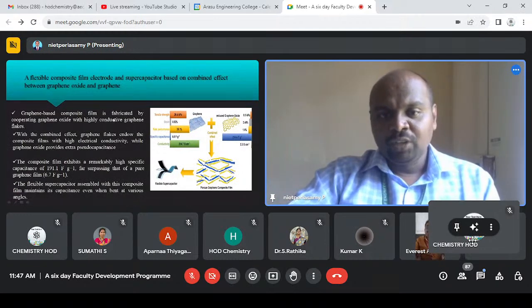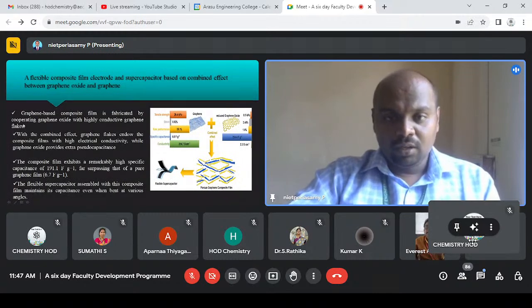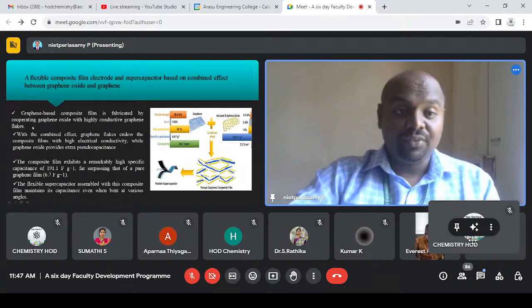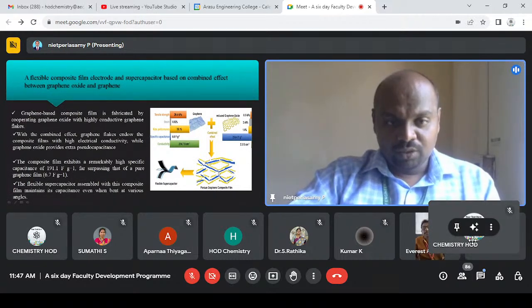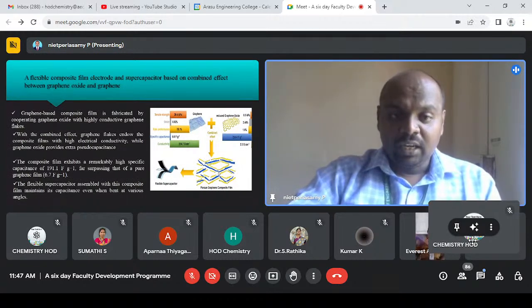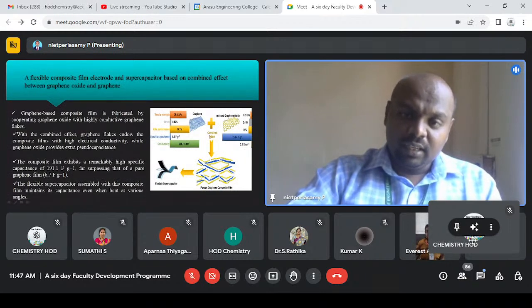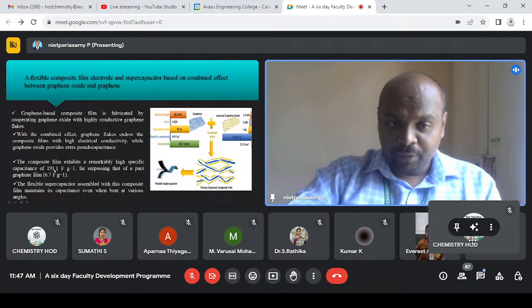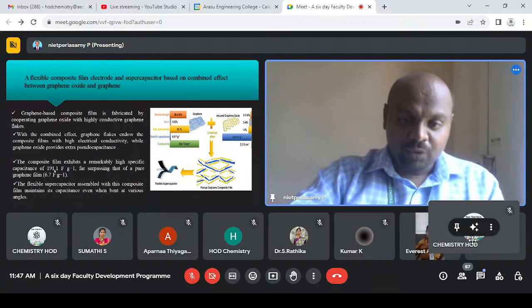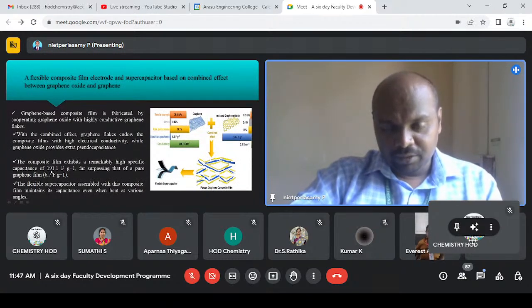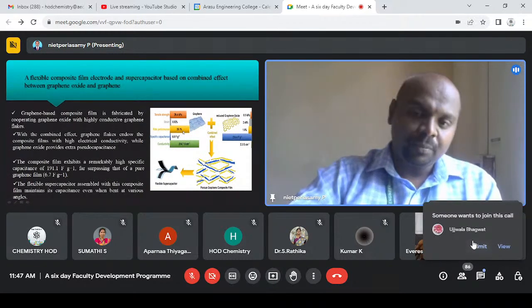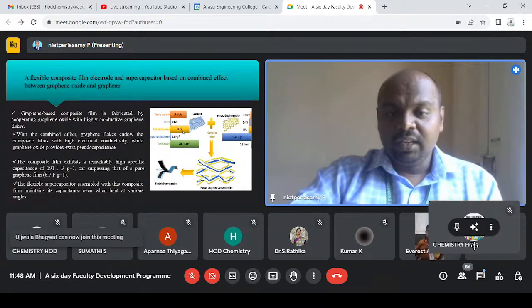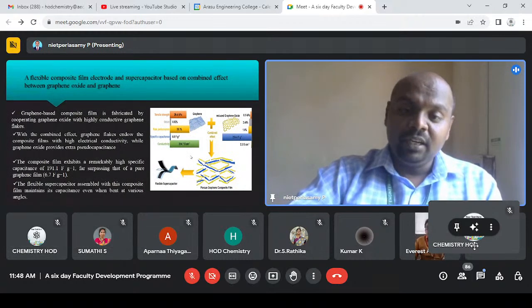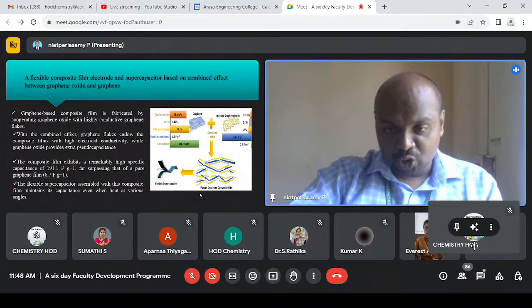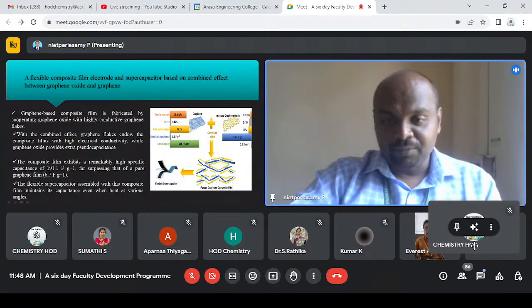Here the graphene-based composite films are prepared by incorporating graphene oxide with highly conductive graphene flakes. You can see the graphene flakes here. With this combined effect, it exhibits high electrical conductivity and provides extra pseudocapacitance. In this report they have reported a specific capacitance of 91.1 F/g, and you might think that it is low, but this is sufficient for preparing low-voltage supercapacitors. These supercapacitors are highly flexible and we can bend them. On the top side you can see the flexible supercapacitors prepared from the porous graphene composite films.